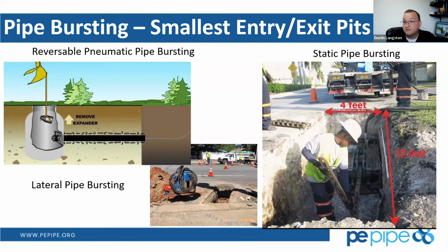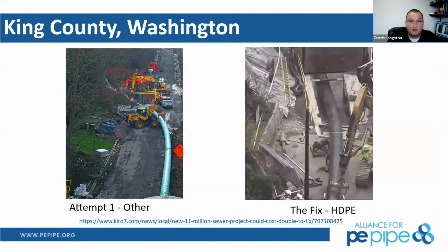And I will also mention that polyethylene pipe is the only allowed pipe material in pneumatic pipe bursting for sewers, because that is such a violent process using a pneumatic hammer at the beginning of the line, that there's no other pipe material that can hold up to that cyclic stress of pneumatic pipe bursting. So it's just polyethylene.